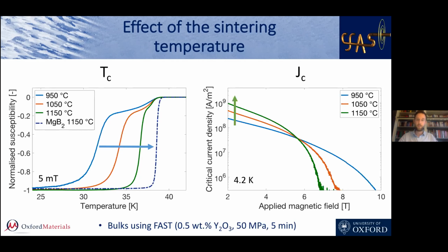So if we increase the processing temperature, we have better connectivity, better macroscopic current loops, and so we increase the JC at low field. However, in here, because we don't have just MgB2 anymore, we have those small precipitates, the effect of coarsening is seen much more. And basically we can see with the red arrow that as we increase the temperature, we increase coarsening and we reduce dramatically the high field improvement that we had by putting in those new pinning centers. And you can see that actually the curve kind of rotates around a point there. And it shows that there is clearly a compromise between better connectivity and coarsening.